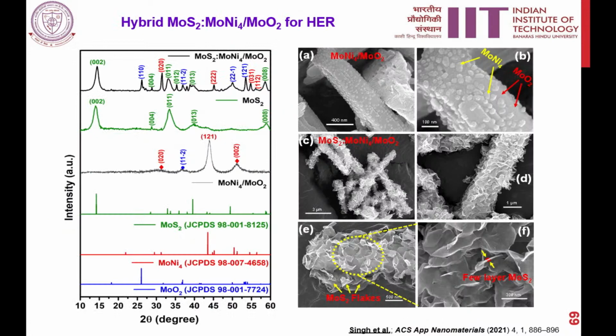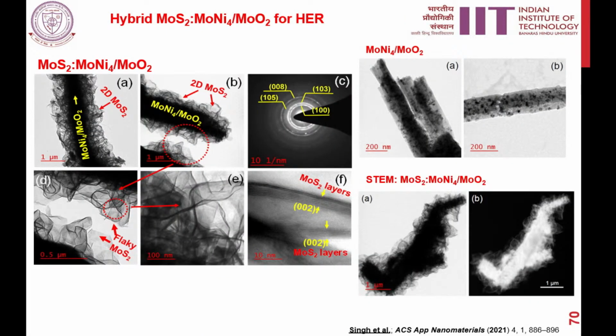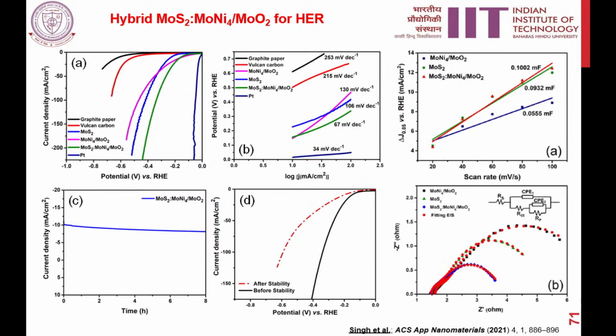First of all, this MoNi4 is metallic in nature, so they are sometimes unstable. Having MoS2 on the surface, they have their edge plane vertically grown on the surface, having few layer MoS2. If you look at this TEM, this flaky MoS2 has a sharp edge plane structure, and this edge plane structure gives us an idea how charge transfer occurs on the MoS2 surface. So we can confirm that vertically grown MoS2 takes place. So the catalytic activity was improved.